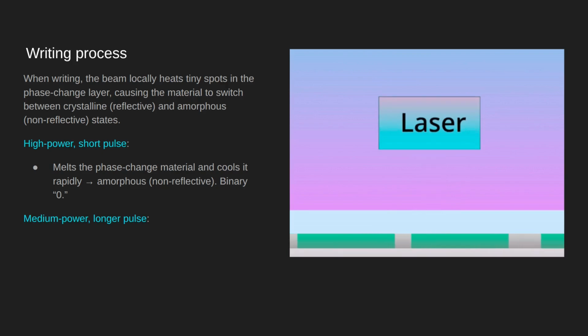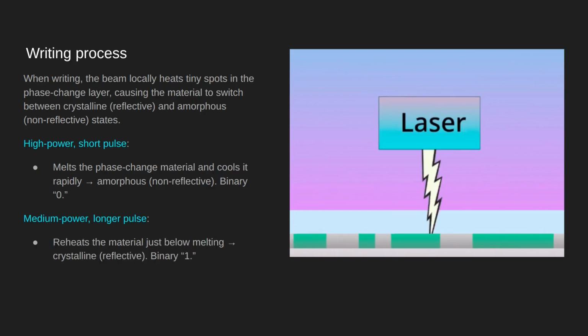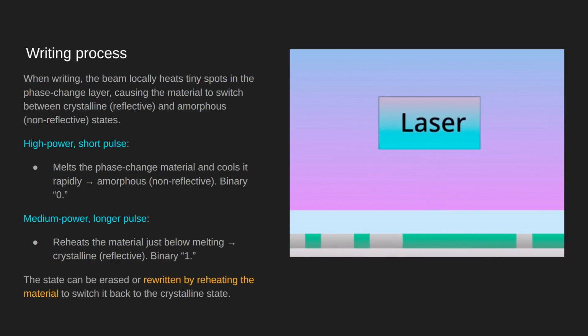Or the other way we can do it, as you can see here with the slightly dimmer laser light, is a medium power longer pulse. Now this is still a higher power than you would use to read, but it's less than the power of the short pulse. And because it's got less power, but we do it for longer, what this does is it holds the temperature just below melting point for quite a while. And this gives the alloy, the phase change layer underneath, a chance to crystallize. And because it crystallizes, it becomes reflective. And therefore, it becomes a binary 1.